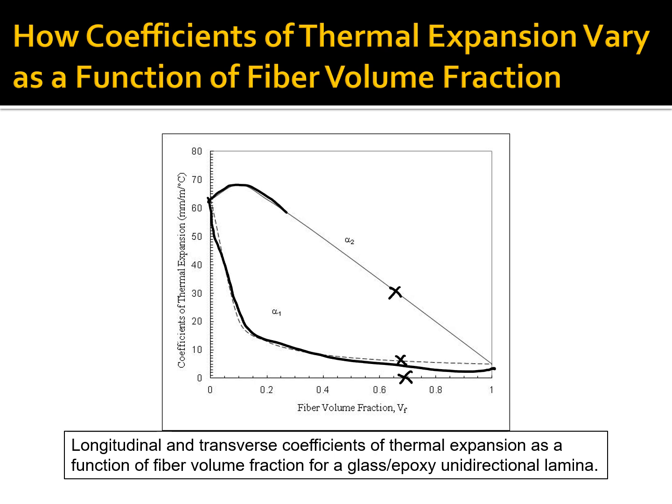However, look at this alpha 2. Alpha 2 is not in between the values of alpha m and alpha f. The value of alpha 1 is, of course, between the thermal expansion coefficient of the fiber and the matrix, but not for alpha 2. Alpha 2 is turning out to be greater than alpha m for this particular fiber volume fraction.